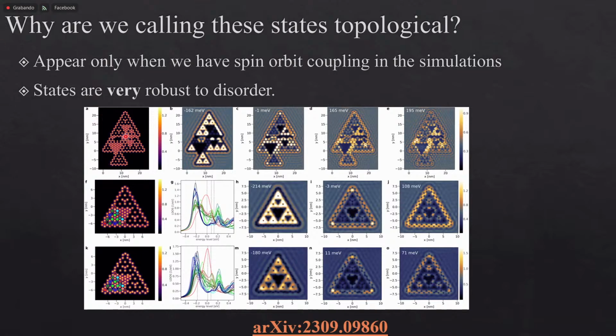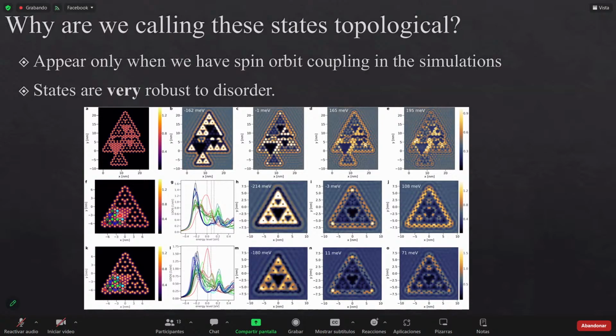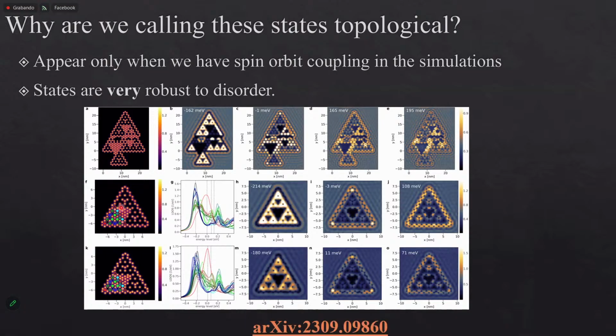And then we add disorder, like a lot of different shapes on the system, because if you remember, the original experimental picture was quite nanoscopic, so you see a lot of different shapes. We could do that, and we see that these states still survive. You have the topological states here that survive, and when you look at a lot of flakes, they are a bit more chaotic. We did also, it's not very clear to see, but I can show the pictures if you wish, more disorder. Here I'm adding disorder in the values of the height of the potential that confines the electrons, and we can see that the states don't change. The same with disorder in the position of the scatterers. So basically it's a way of making the system more amorphous, and we don't see the states changing here.